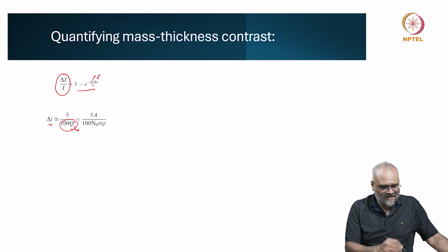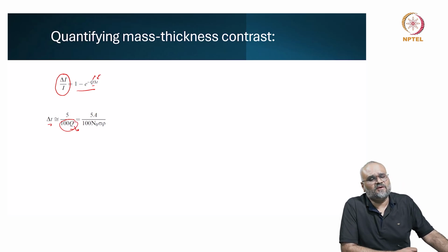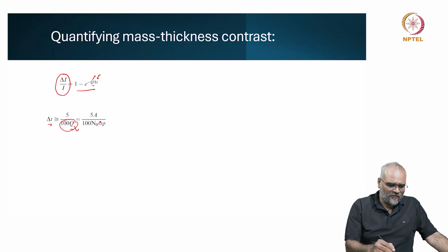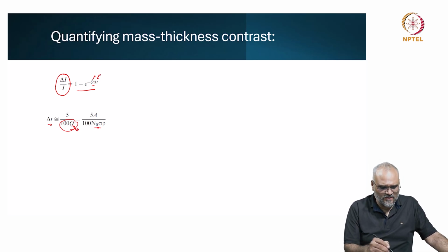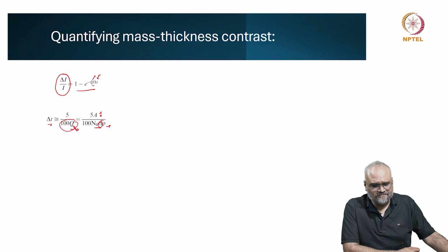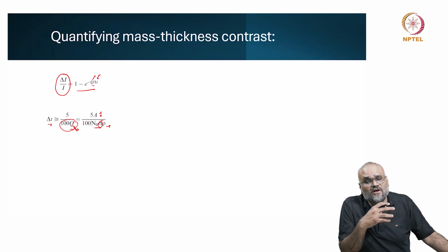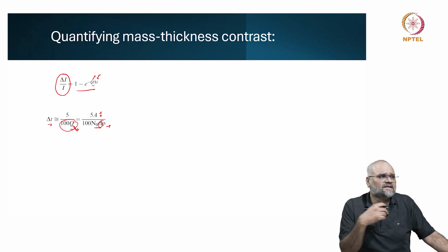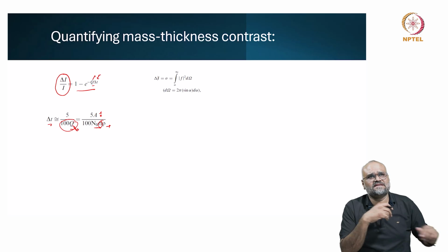I can fill in q from the ideas of scattering cross section that were introduced a few lectures ago on Rutherford backscattering. You can plug in this q in terms of the Avogadro number, the scattering cross section, density of the sample, and the atomic weight. You can also write this in an integral form which appears like this.